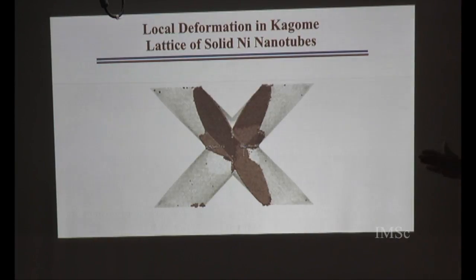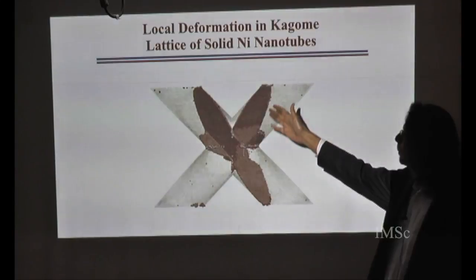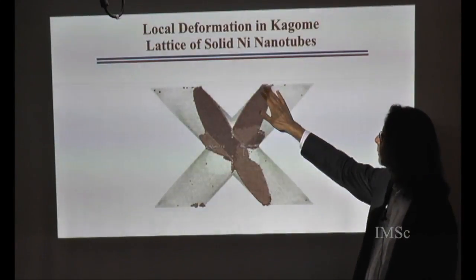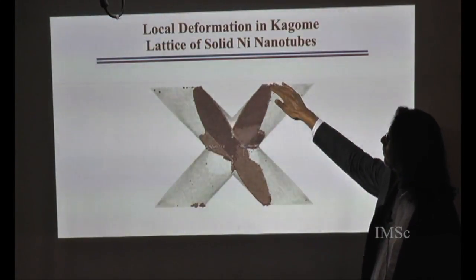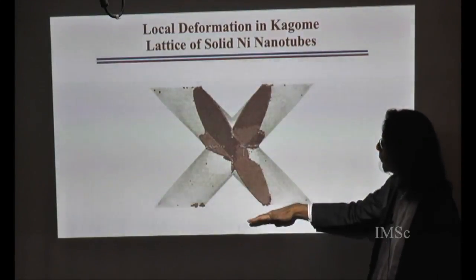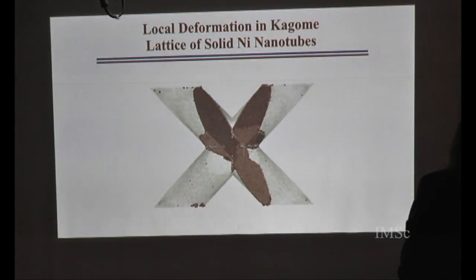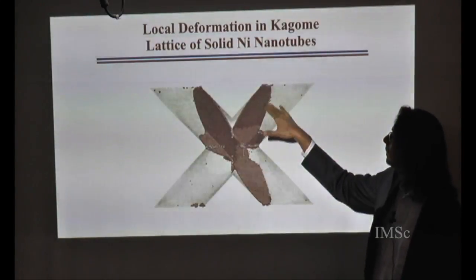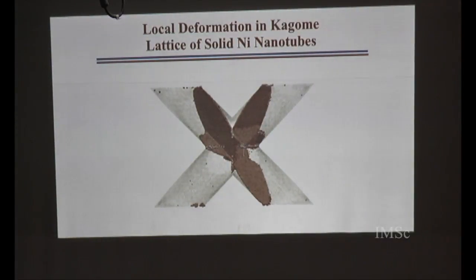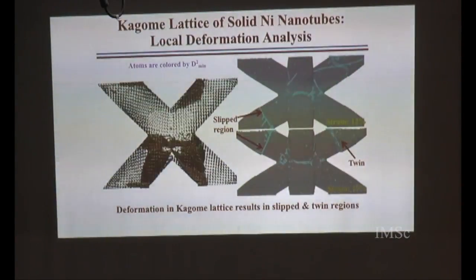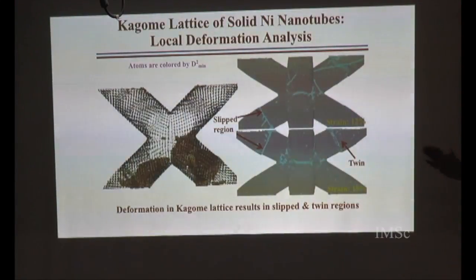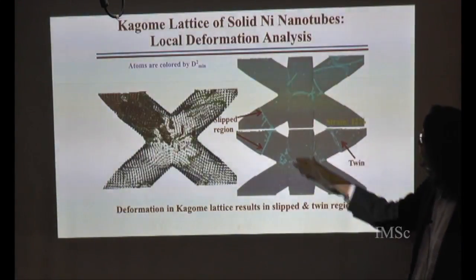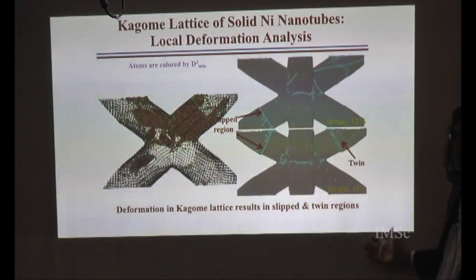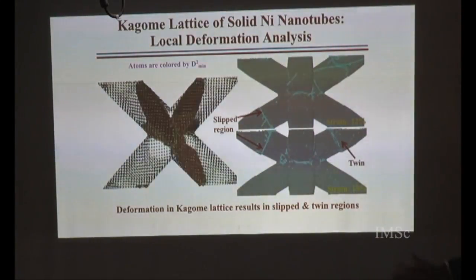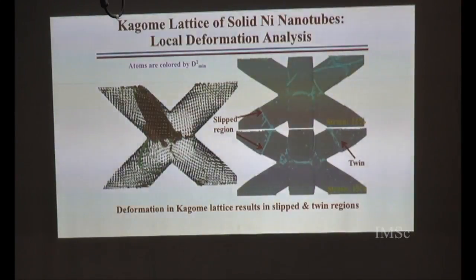In this case, the local deformation analysis corroborates what I was telling earlier, that dislocations start from the flat punch and also from the substrate, and travel to the middle. And this is where most of the local deformation is. And then in this case, in the solid nanotubes, we also see other kinds of things. We see slipped regions, twins, for example, in the system. And this is one snapshot at 12% strain.